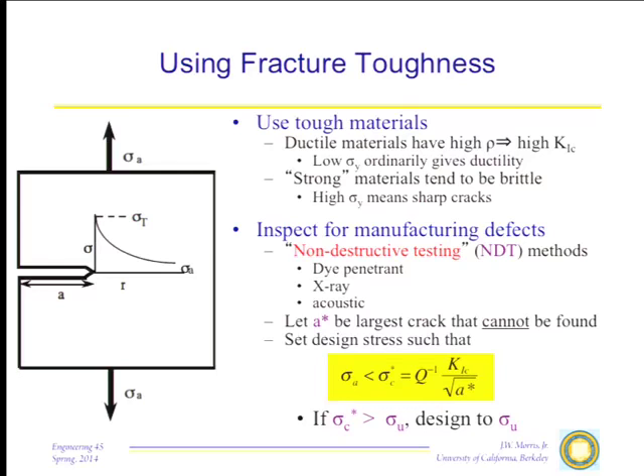There are various techniques, dye penetrant, x-rays, acoustics, that you use to go looking for cracks in material. Then what they did, none of these non-destructive testing techniques are perfect. So they said, let's find what we can detect with the techniques that we can fairly easily use. So you take the technique you're going to use for non-destructive testing, and you let A star be the largest crack that can't be found.